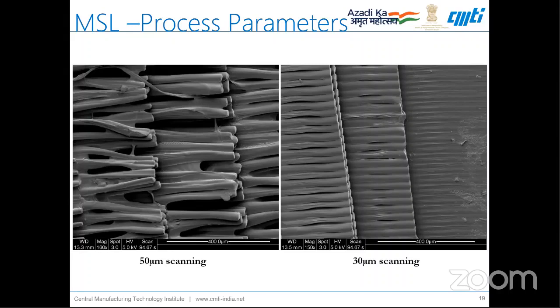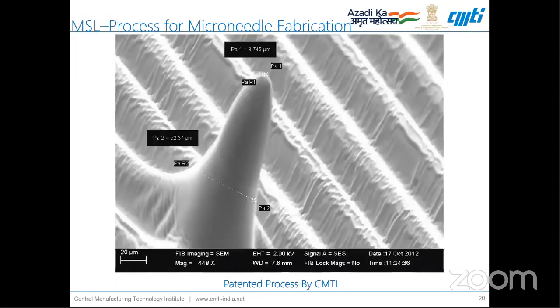So here, by conditioning the beam when you're projecting onto the photocurable polymer, you are able to get a 3 micron resolution, maybe 1 micron resolution also. So this is one patented process, the CMTI. You can see here the fabrication of microneedles. These microneedles are fabricated using this technique.